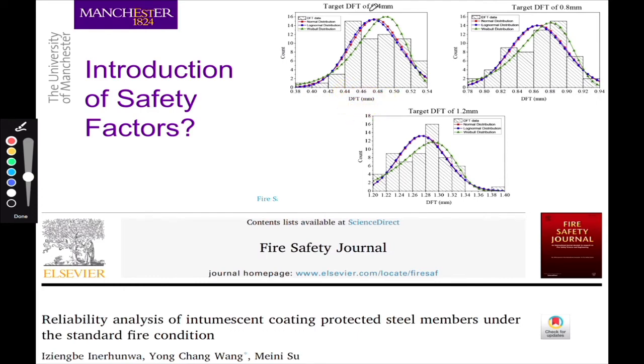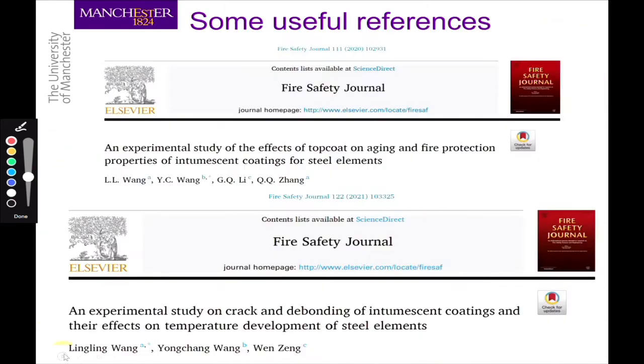So if, for example, we say the dry film thickness is 0.4 millimeter, in fact there can be a range of values that you would get in real life, as in other coating thicknesses. So putting things together, we have carried out a probabilistic modeling of structure behavior with these variabilities, and have derived a number of safety factors, depending on failure probability. Again, you can find our results in this paper. So that's on intumescent coating.